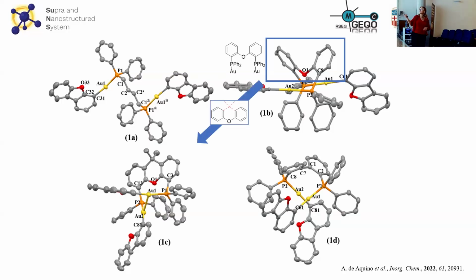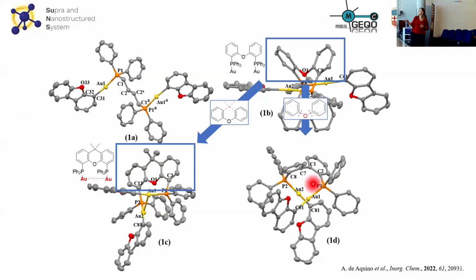But we can close this diphosphine a little bit more, and in this case, with this bridging ligand called Xantphos, the diphosphine, we can enhance the approach between the metal centers. And in this case, we do have the presence of these aurophilic interactions. The same happens in this case with the diphenylphosphine bridging ligand, as we can observe here. I would like to say that here we do not have any type of aurophilic contacts. Here we have intramolecular aurophilic interactions. And here, what we observe is that there are aurophilic interactions, but between molecules, in an intermolecular way. Okay, so this is the difference.